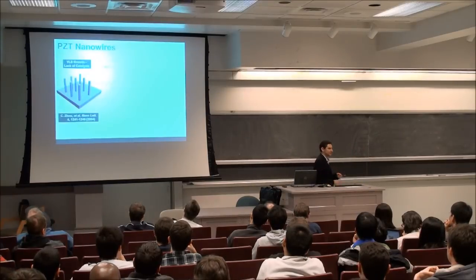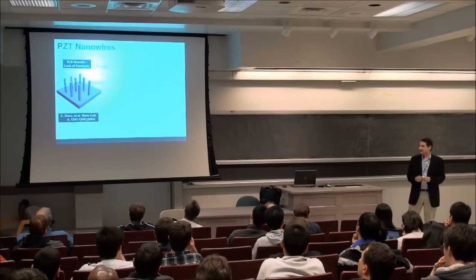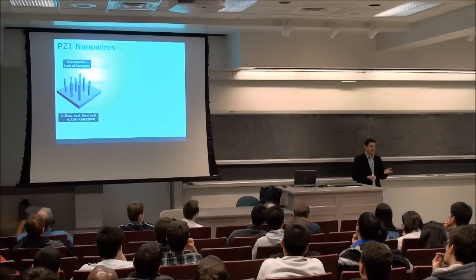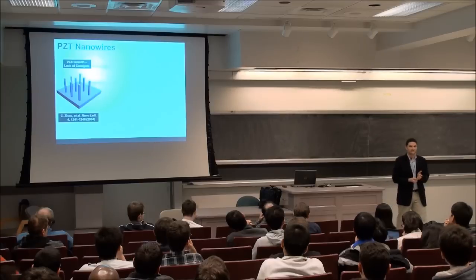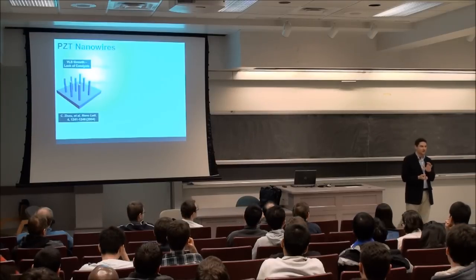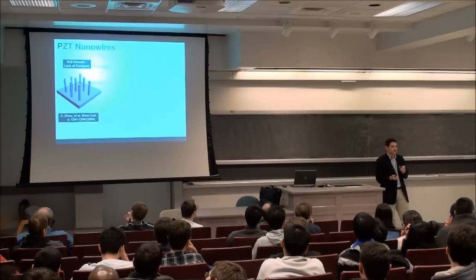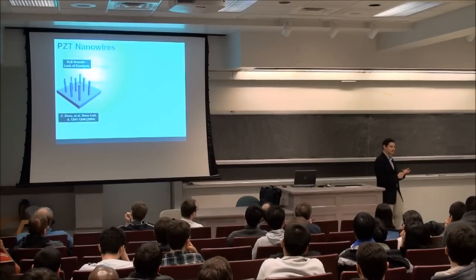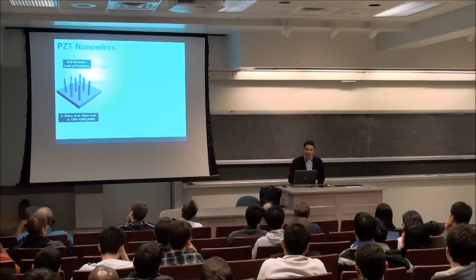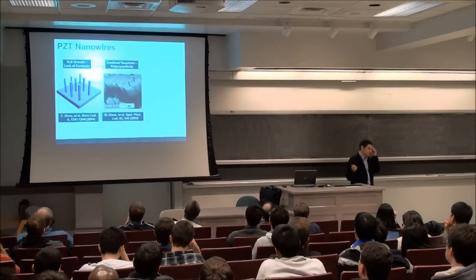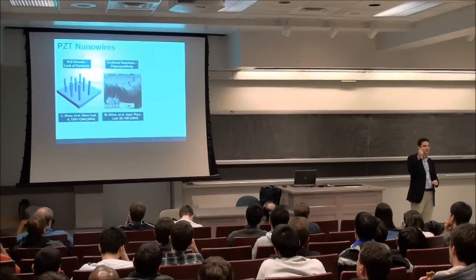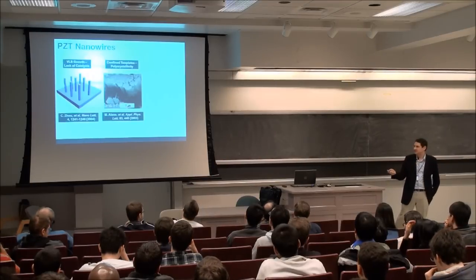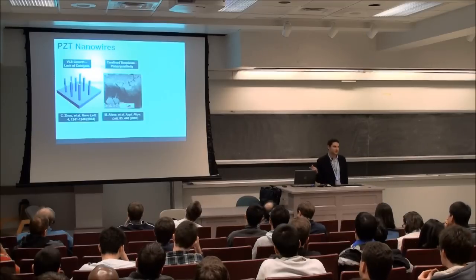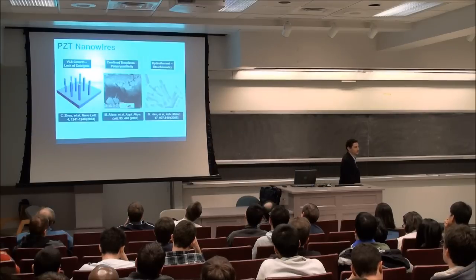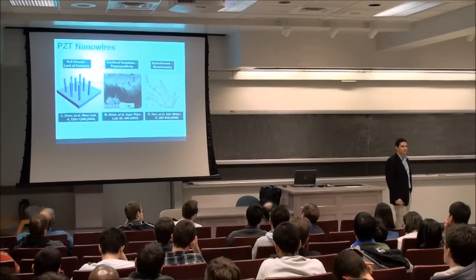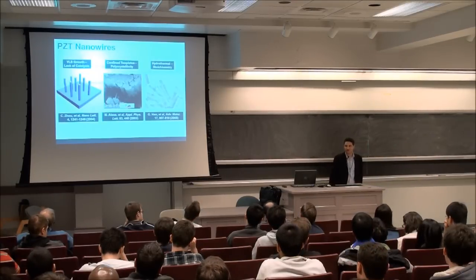But more recently, I've been interested in PZT for the reasons I mentioned before, but also because it's very difficult to make nanowires out of PZT. These days, nanowires have been made out of pretty much any material except PZT and materials like that. The reason is that you can't do the VLS approach that you normally use for growing nanowires, because you can't get a catalyst that can solubilize lead, zirconium, titanium, all these different components of PZT, and then grow them in idealized ways. The first approach was a paper by Chongwu Zhou at USC, where he grew magnesium oxide templates using VLS and then deposited PZT on top of it. You can use confined templates, these alumina templates, but you get polycrystalline PZT, which lowers your d33 value. Or you can use hydrothermal approaches, but it's difficult to get the correct stoichiometry, which you need in PZT to get the highest d value.